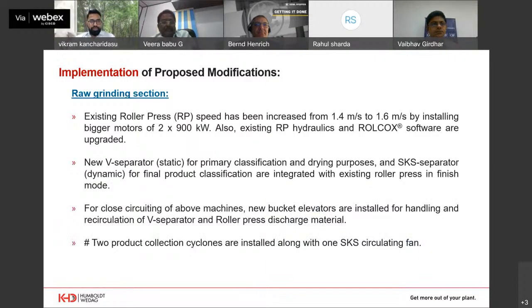In the clinker cooler, the complete moving grate has been modified. In the kiln bag house, the capacity has been enhanced and the kiln bag house fan is installed. In the fine coal dosing system, new Coriolis feeders of 10 TPH each for the kiln burner as well as the calciner burner are installed. In the raw grinding section, because on one side we are increasing the capacity of the pyro system, the raw grinding capacity should be suitable for catering to that requirement.